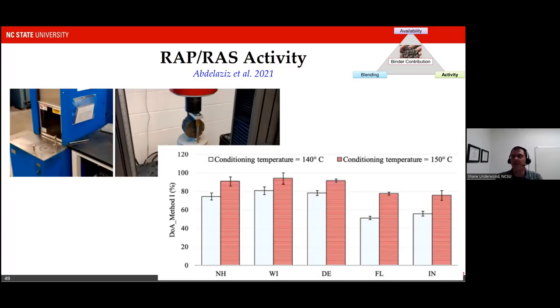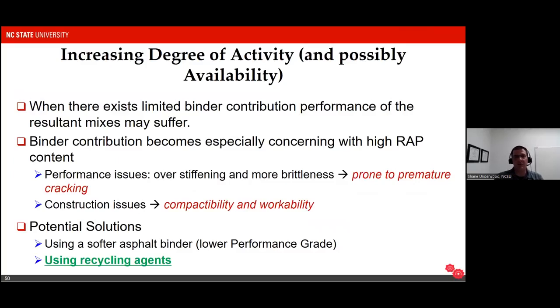So when we have limited activity, the mixture may perform in an inferior way. This becomes increasingly important when we start thinking about cracking, because when we develop the mixtures, we assume that the binder that's there is all acting. It's active, it's available, and it's contributing positively to the performance of the mixture. But in fact, the recent literature on this tells us that not all of that binder is active. And so we actually have a much lower effective binder content in our mixtures. And heretofore, we haven't been characterizing this, which is one reason that you can see some mixes doing a very, very good job and other mixes doing a very poor job, because they're giving you different availability, different activity, and so on.